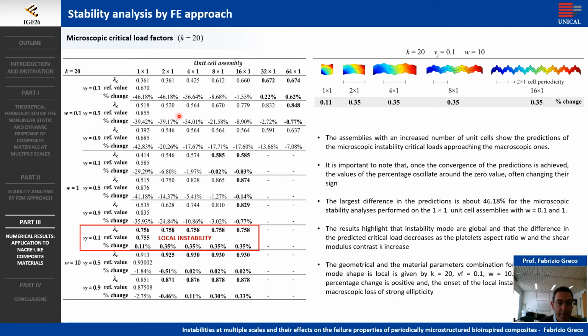The results highlight that, generally speaking, prime instability modes are global in nature, and that the difference in the predicted critical load decreases as the platelet aspect ratio W and the shear modulus contrast K increase. Results show, in addition, that the geometric and material parameters combination for which the critical mode shape is local is given by K equal to 20, platelet volume fraction 0.1, and platelet aspect ratio W equal to 10. The local microscopic instability mode, characterized by finite wavelength, has a periodicity corresponding to a 2x1 unit cell assembly, as shown in the picture.